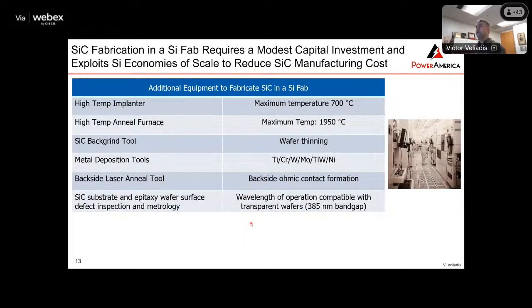Okay, so having said all that, if you have a silicon fab and you want to fabricate silicon carbide, this is a list of the main tools you need to purchase that are not available in your silicon fab. High temperature implanter, an anneal, where you can basically anneal the wafer after you do the implantation. You need a backgrind tool to thin the substrate to reduce the resistance of the substrate.